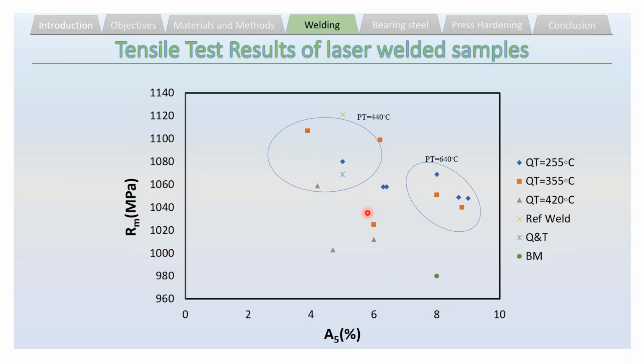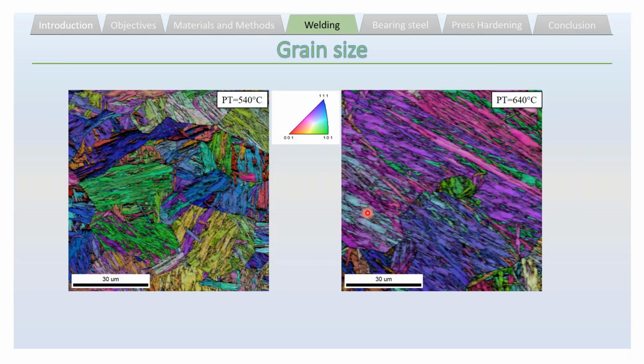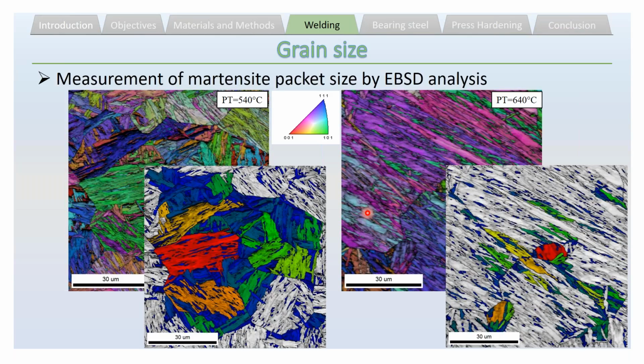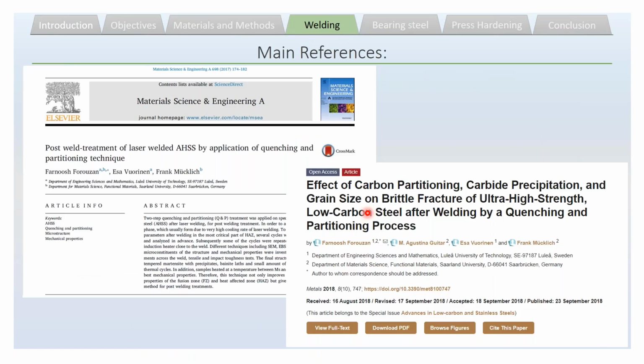But what is important, and we saw, is whether there is any grain growth. And you know that the structure is martensitic, so it's not possible to do a normal measurement of the grain. So we need to do EBSD and measure the packet size of martensite. But what was very interesting was that at 640, we saw very huge grains, which are approximately nine times bigger than what we saw in 540. So here you can see the grains inside this margin, and these huge grains can decrease the toughness very much. So the best condition that we found was at 540.